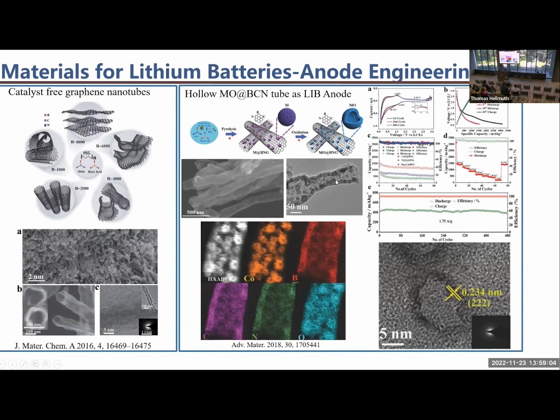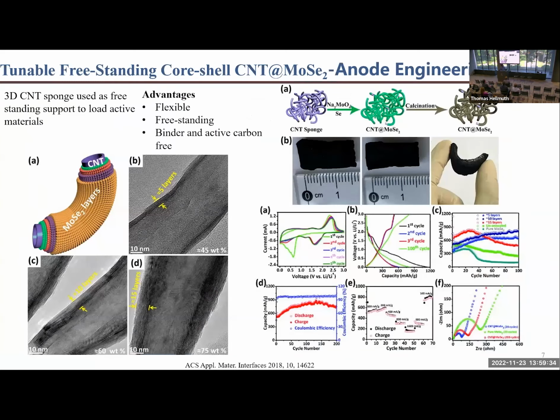And to further stabilize, we created empty spaces inside the particles by a second heat treatment. This provides enough space for reversible volume expansion of the particles. Together, these hybrid materials delivered very good capacity, around 1,400 milliampere hour per gram. That's nearly 4 times that of graphite, and also very good stability up to several hundred cycles. Just to say, there is a flexibility in material design. We can design materials in a number of ways. This is just one of them.